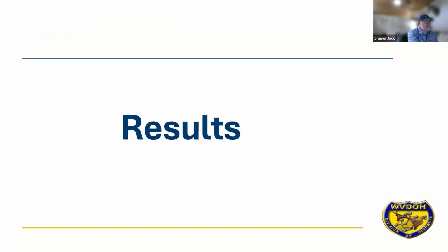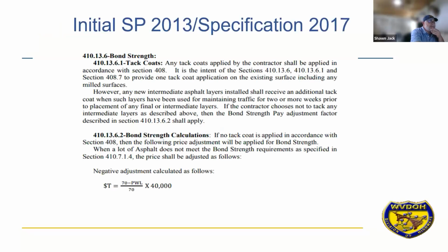All right, results. So our initial special provision was written in 2013, and it didn't change, but it became a full specification in 2017. But essentially, as you can see here, we said that if you use a tack coat, the negative adjustment does not apply. So if no tack coat is applied in accordance with Section 408, which is our tack specification, then the following price adjustment will be applied for bond strength.